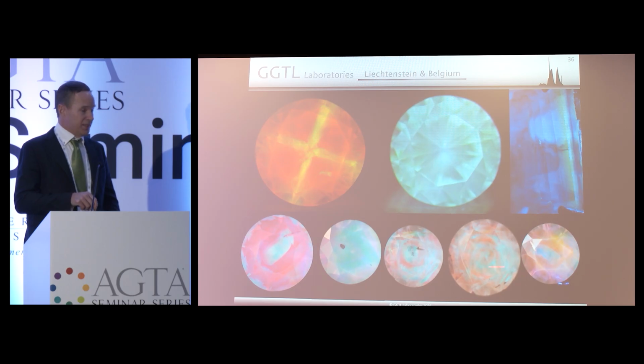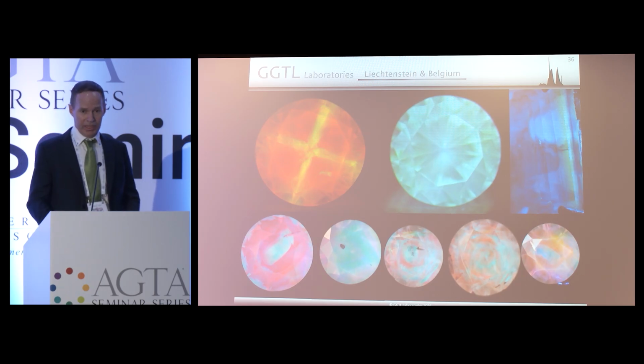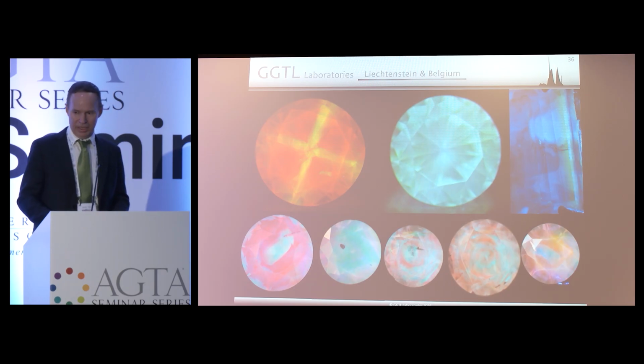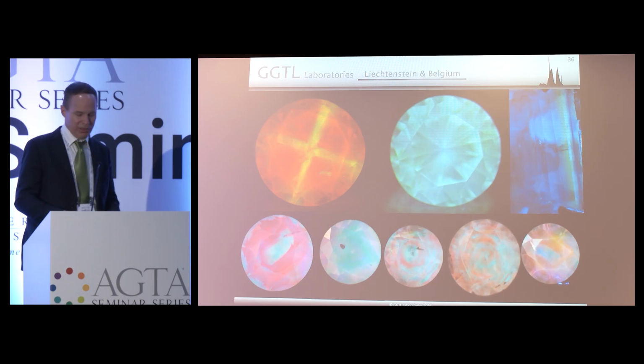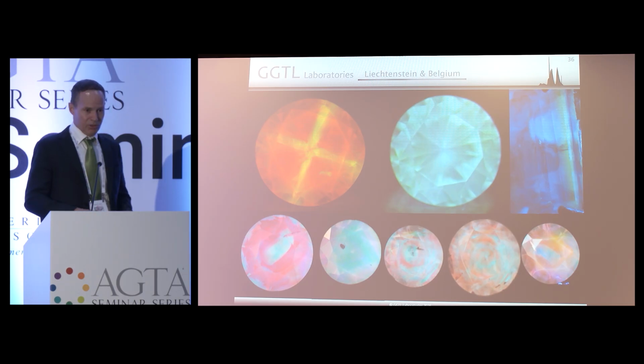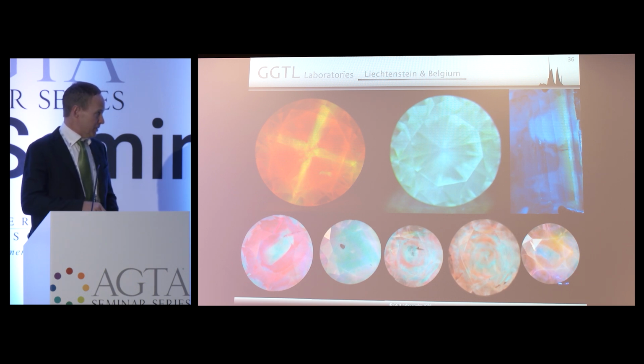This material is easily identified since natural pink type 1A material, the Argyle material, for example, all fluoresces blue, almost exclusively. I've never seen an Argyle that fluoresced anything but blue to maybe slightly greenish blue, but it's generally blue, blue, blue, no matter what excitation you use. So this kind of response will tell you your stone has been treated.